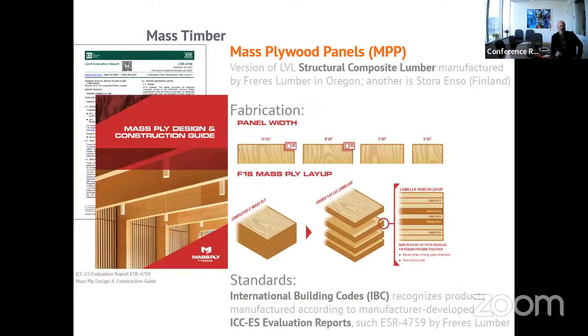Essentially, what's done here is similar to the CLT. We have alternating orientations of the veneers. In this case, the orientation can be predominantly in one direction with a few plies in the opposite direction. We can see that in this image here, where most of the plies are laminated in the longitudinal direction of the panel, with a few plies going the other direction. And then these are built up as multiple thinner, about 2 to 2.5 centimeter thick panels, married together to produce something that could be in the range of 20 to 40 centimeters. These can be used, as shown in the image here, both horizontally and vertically as framing members, as well as horizontal panels for roofs and floors.